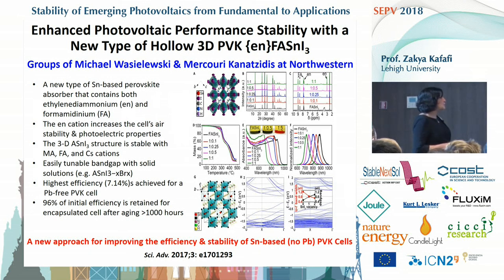These have easily tunable gaps with solid solution, and they demonstrated fairly high efficiency for this lead-free type of perovskite cell. 96% of the initial efficiency was retained for the encapsulated cell after more than 1,000 hours of aging process.